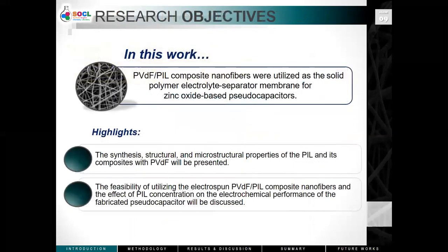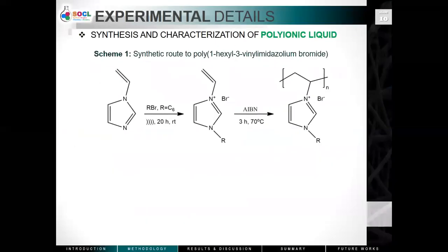In this study, PVDF PIL composite nanofibers were utilized as solid polymer electrolyte separator membrane for zinc oxide-based pseudocapacitors. The synthesis, structural, and microstructural properties of the PIL and its composites with PVDF will be presented, and the feasibility of utilizing the electrospun composite nanofibers and the effect of PIL concentration on the electrochemical performance of the fabricated pseudocapacitor will be discussed. To carry out our objectives, a two-step synthesis was employed to prepare the target PIL.